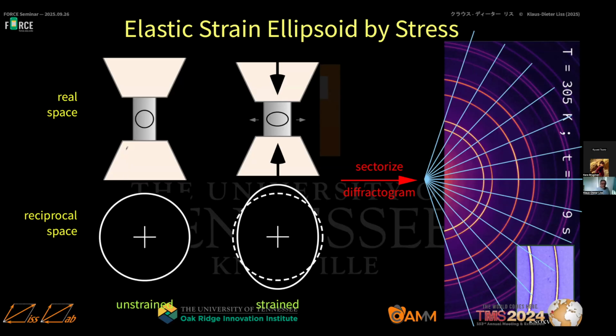In real space here, if we have a specimen and we look to the orientation dependence, and it's internally stress-free, then the lattice plane spacings are in all directions the same. There's no elastic strain. In reciprocal space, the Debye ring, looking to a family of planes, is just a circle. Now, if we compress as here, then we can see that we get a strain ellipsoid because we compress in a vertical direction in real space, so the distances between the atoms become smaller, and laterally, according to Poisson's ratio, they become larger. So we get an ellipsoid.